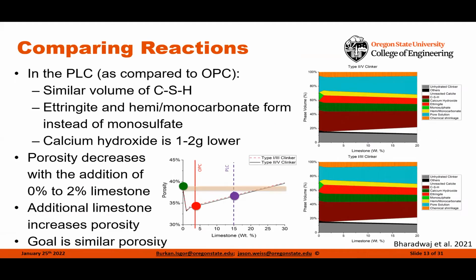In addition, we've been able to use this to really start to describe for a lot of groups how we can make this transition from an ASTM C150 cement over to an ASTM C595 or Portland limestone cement in the system. And what we've been able to do is really build on a lot of the work that's been out there, where we're able to look at how the porosity of the system starts to change. And it's really changing because of some of the phases that are forming in the system.